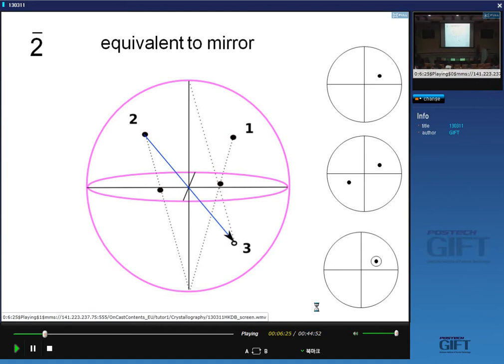And if we now forget about this three-dimensional diagram, it's very easy. Here I rotate through 180 degrees about the north-south pole, which is pointing upwards. I produce this point. If I invert it through the center, I reproduce a circle which is in the lower half of the hemisphere. Okay. And this equatorial plane is the mirror plane. It's at 90 degrees to that twofold rotation axis.